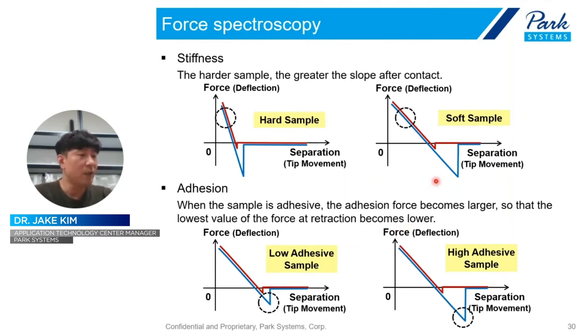This slide shows some examples of FD curves in each case. Let's say in the case of a hard sample, a hard sample has a quite stiff slope of the approach curve like this. But in the soft sample case, you can see a relatively broad slope compared with this hard sample. Also, in the adhesion case, if the sample has a low adhesion, like a low adhesive sample, this adhesion value will be low like this. But a high adhesive sample, like a sticky sample, has a quite high adhesion force.